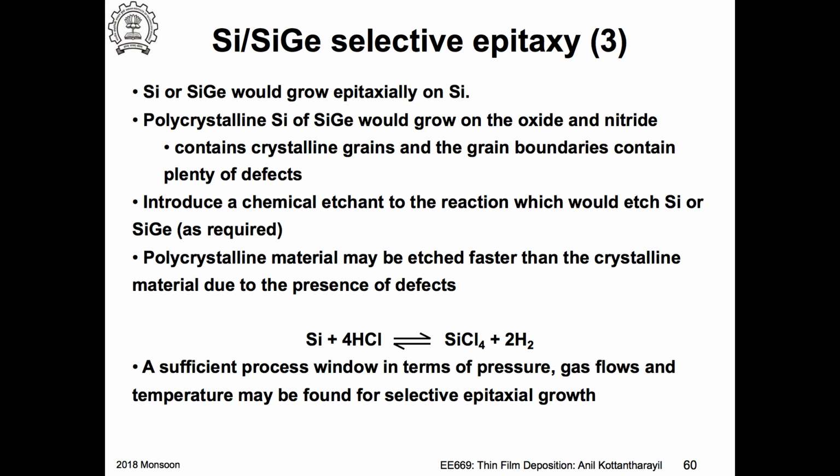Okay. So you are actually depositing and etching, right? And wherever polycrystalline is deposited, the etch rate is faster.